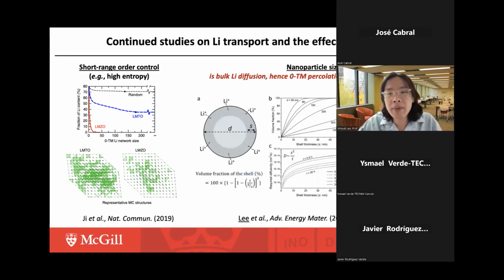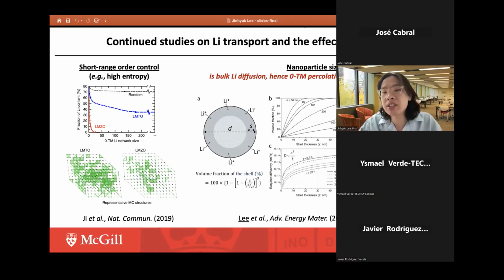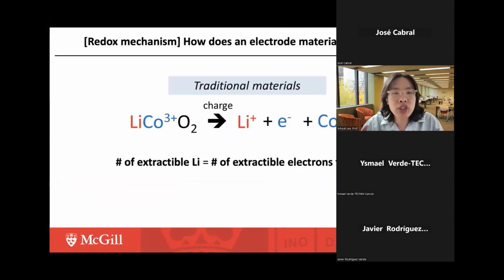And also recently, I've shown that particle size actually becomes very important when we determine the necessity of lithium excess to develop high capacity DRX cathode materials. In this paper, I show that in fact we don't need lithium excess for certain kinds of DRX material when they're made into nanoparticles. So I would like to say that overall, there must be more fundamental understanding of this lithium-excess effect and the lithium transport mechanism. So with that, let me change gear and now discuss the redox mechanism.